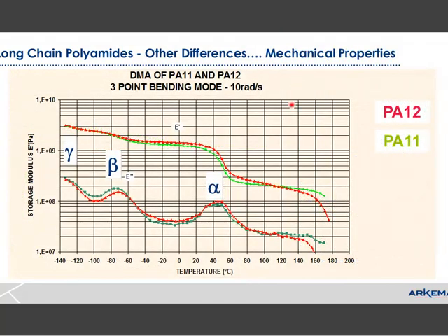This last slide, I threw this in just for general information. It's comparing PA11 and PA12. And all I want to point out here on this slide is this particular thermal transition, the low temperature, which controls low temperature properties. PA11 is a little bit better than PA12, and you probably get another 5 or 10 degrees C of performance if you needed it at those low temperatures.